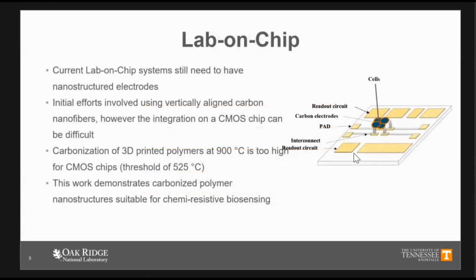So the motivation behind this project was that we still need carbon nanoelectrodes or nanostructured electrodes for lab-on-chip systems. And the initial efforts that we have done were based on the alignment of carbon nanofibers. However, the integration with CMOS is very difficult in that temperature range, because as you know, pyrolysis of these polymers happens around 950 to 1000 degrees Celsius, but that is destructive for any kind of CMOS circuitry. So our goal was to decrease that temperature range down to 500 to 600 degrees Celsius, where our CMOS circuit can survive, and we can create these systems together.